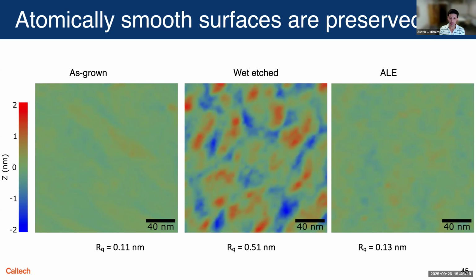And so this is very important. The low roughness is a reasonable indicator that the surface is electrically good, although not guaranteed, but it's an indicator. And the roughness also impacts the transconductance. If the surface is smoother, the transconductance in general will be higher. So there's a lot of positive indications for the surface quality of this ALE.